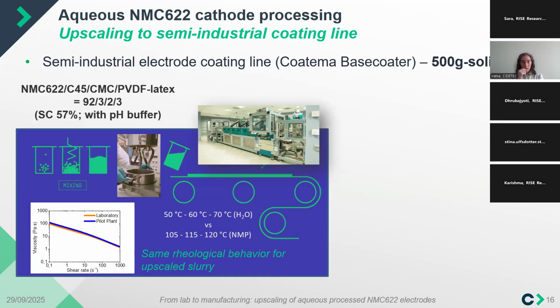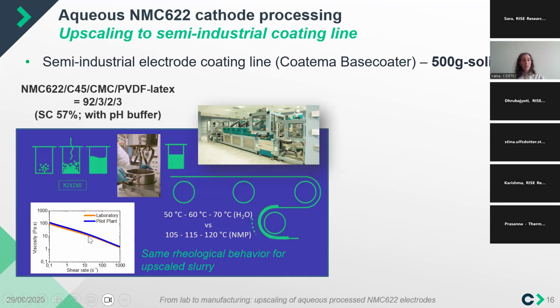For instance, in this example, going to at least 1 liter slurries, around 50% solid content, or 57%, with this PVDF latex—a stable suspension in water of the PVDF—there are no changes between the pilot plant, this larger slurry, and the lab scale. That's something better to confirm every time at different upscaling steps.